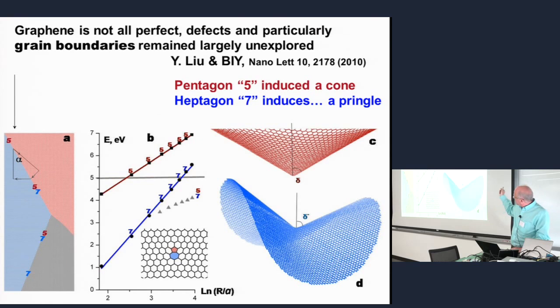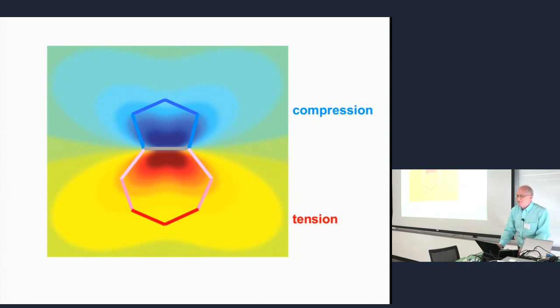If you have perfect lattice of graphene, if you introduce just one pentagon, it's easy to see that it will create a cone. If you introduce one heptagon, it will create what we call a Pringle, because it's like this saddle point. And then, of course, if you join them together, it brings you this familiar 5-7, which is a dislocation. So disclination strength of it is 0, but Burgers vector is not 0. Its energy is about 5 eV, but very hard to define. It's actually still an unsolved conceptual problem what is the energy of dislocation in the two-dimensional case, because convergences are very slow.